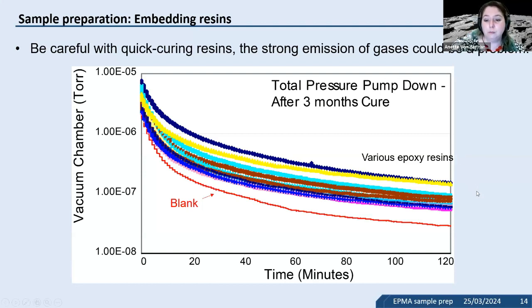The University of Edinburgh has a great little webpage on their SIMS site. I have the link in a moment, where they looked at various epoxy resins for certain key factors. What you see here is the pump down time in minutes and the vacuum chamber vacuum. Again, it's a logarithmic scale, and you can see that the initial pump down can differ very much, and specifically what achievable vacuum we have. And the better the vacuum, the better our analysis, essentially.